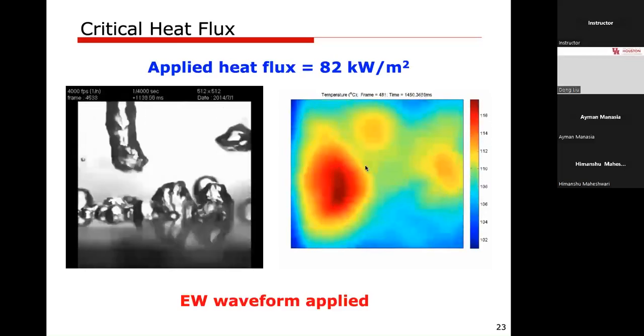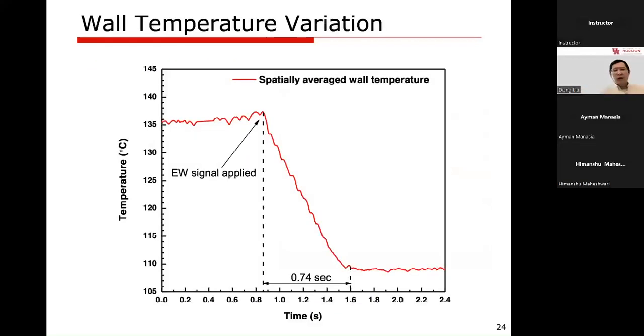Okay. So to see the effect more clearly, let's move on to this slide. So this tells you the average temperature of the entire boiling surface as a function of time. So before the electrowetting effect kicks in, the average temperature is 135 degrees. Now after, it reduces to 110 degrees. Now the amazing thing is how quickly this can happen. So basically, once you click the button, within a fraction of a second, so 0.74 seconds, you can change the temperature by so much. Right? So that illustrates how effective the electrowetting effect is in terms of enhancing boiling.